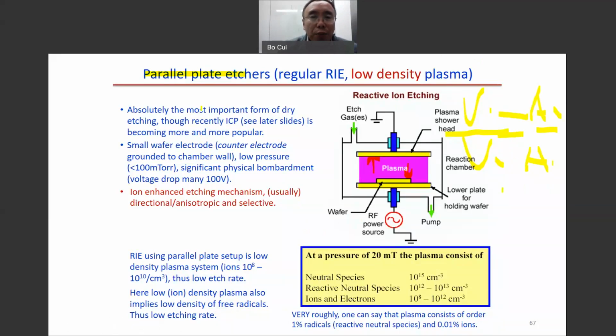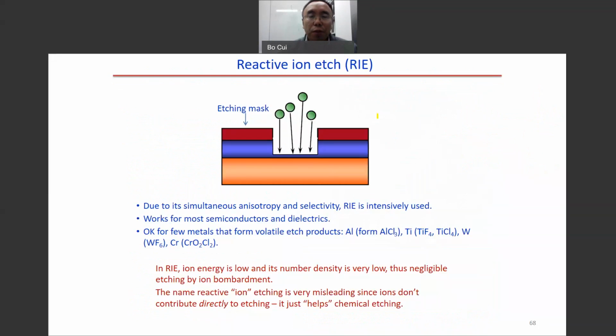But the RIE profile for this process is a low density plasma. As you can see, the neutral species, this is the gas molecule, for example, CF4 gas is 10 to the power 15. But the reactive neutral species is 10 to the power 12. The ions and electrons are only 10 to the power 8 to 10 to the power 12. So very low plasma density. So this is not very good. So this is the RIE summary.